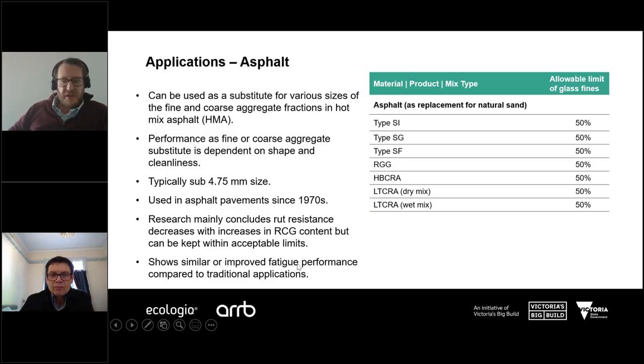I guess another one of those concerns is that the adhesion is also related to the specific surface area of the aggregate in question, and therefore, due to the slightly smoother surface texture of recycled crushed glass aggregates, there's the potential for a reduction in the stripping resistance in comparison to natural aggregates.